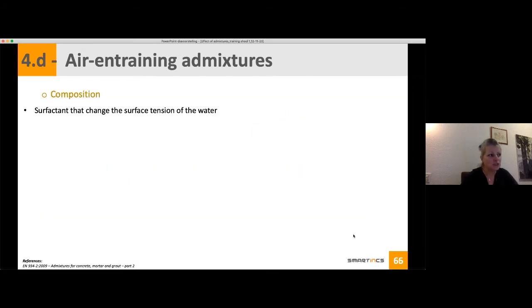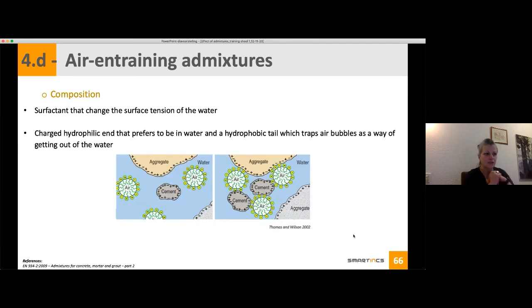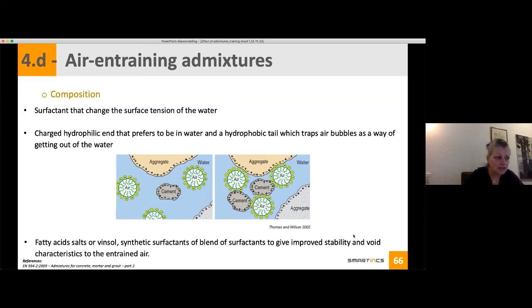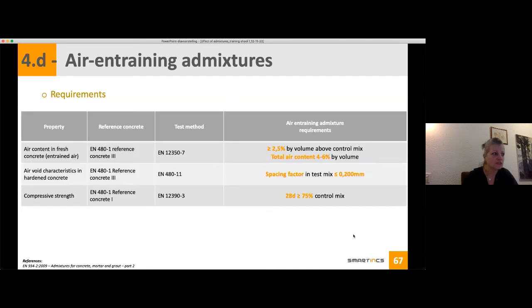So if we look at the composition, it is surfactants. Surfactants are chemicals that have two sides, one hydrophilic and one hydrophobic. You can see it here in the picture, where you have the air and the surfactant, which stabilizes the air. So instead of the air going out of your cement mixture during mixing, it will stay here stabilized, and it will also control the size of the air bubble. Usually it is fatty acid salts. What is also largely used is vinsol resin. And then you can also have synthetic surfactants.